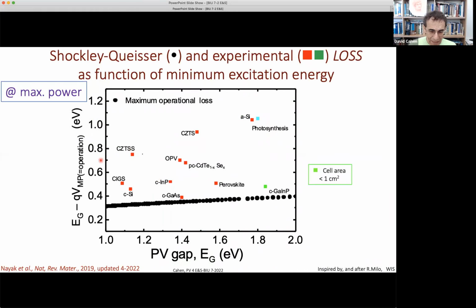So you can make this plot, which I owe to my colleague Ron Milo, or at least the basis for it, and you calculate what will be, according to Shockley-Queisser, the minimal loss that I'll get if I compare the band gap photon energy and that of the voltage at maximum power, which I then have to multiply by the electric charge. And you see there are two that are very close, gallium indium phosphide and gallium arsenide. So we're now not at open circuit, here at maximum power, which is where the cell really matters for us.